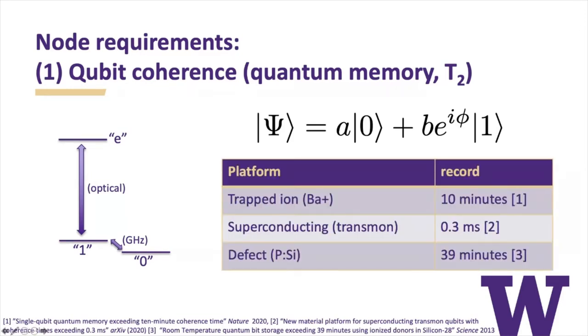So for trapped ions, and I'm showing you world records and some famous platforms, the world record is held by barium, and this is 10 minutes. The superconducting transmon qubit has just broken its record. This is an arXiv paper, which shows they can now get to 0.3 milliseconds. And what may be surprising is that a defect in a crystal can rival these significantly. In fact, the phosphorus dopant in silicon is 39 minutes. That's the record for storing information in this defect system.